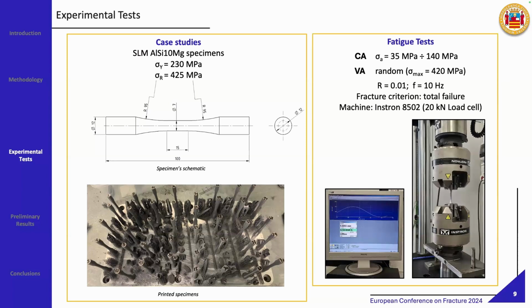So first of all, we carried out constant amplitude tests with stress amplitudes comprised between 35 megapascals and 140 megapascals. Concerning the variable amplitude load, as I showed you in the previous slide, it was a completely random loading sequence characterized by a maximum load relative to a maximum stress of 420 megapascals. The loading ratio was 0.01 and the loading frequency 10 Hertz. Here you can see a picture of a specimen mounted into the testing machine of our lab.